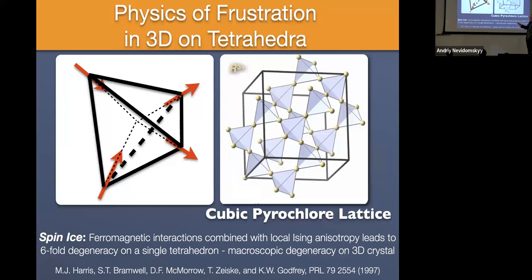So this is going to sound a little bit contrived, but I assure you that it's quite common in nature. You can have magnetic dipole moments that are constrained by crystalline electric field effects, which I'll explain in a few minutes, such that they can only point into or out of the tetrahedron. And the magnetic moments themselves have interactions in which near neighbors would prefer to be aligned parallel to each other. So it's almost a ferromagnet, and in fact, there is a net magnetization to a single tetrahedron. It's pointing from your left to your right, okay? But it's not the magnetization of 4 of the individual spins. It's less than that because the moments are canted to obey their local anisotropy, such that they can only point into or out of the tetrahedron.